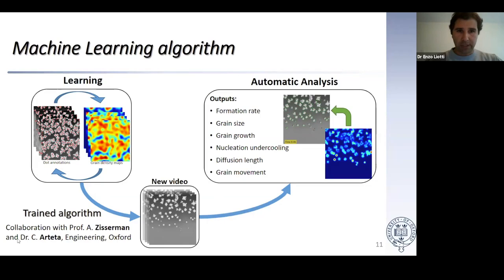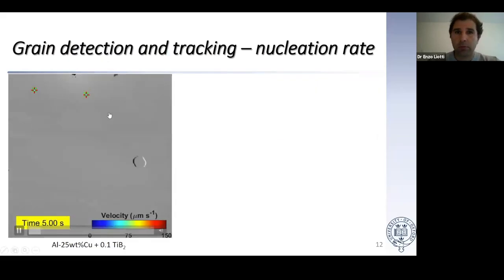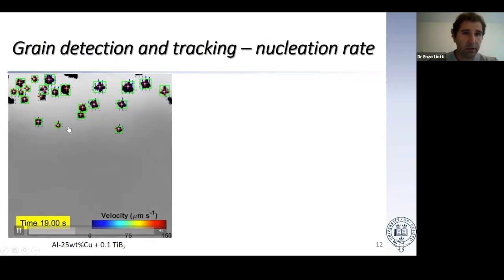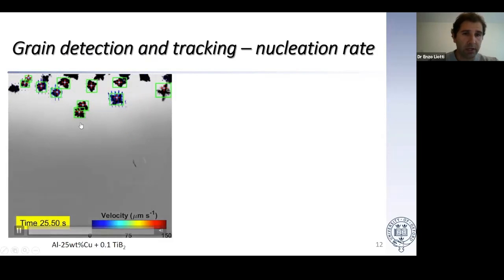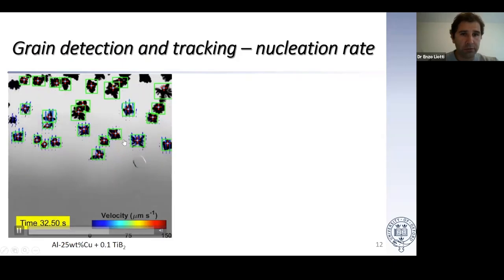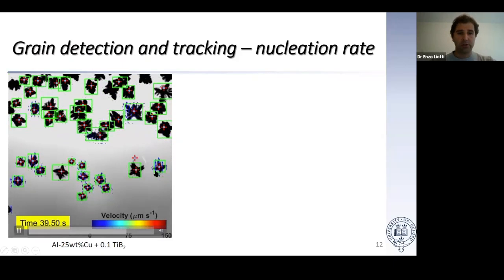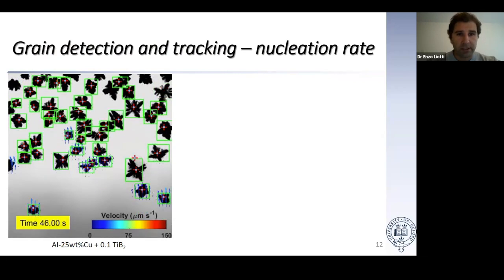The algorithm was outputting a map allocation of the grains, to which we then added a second part that tracked the grains and did the solidification parameter measurements. So it gives output of the formation rate, grain size, grain growth, what we call nucleation undercooling, and other things like the diffusion length, which is a measurement of diffusivity and grain movement. And this is an example. That's the algorithm tracking the grains, detecting them when they form, and the bounding box gives you an idea of the size, although the contour and also the primary and secondary arms are generally tracked. The arrows give you an idea of the velocity. So this is quite rich information that can be extracted, and honestly this cannot be done by hand.